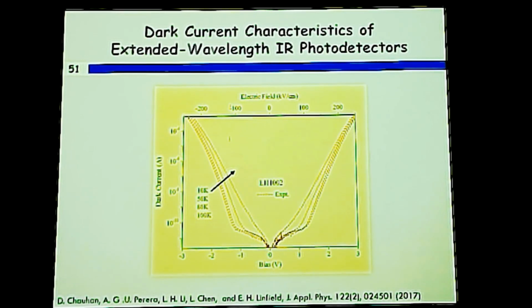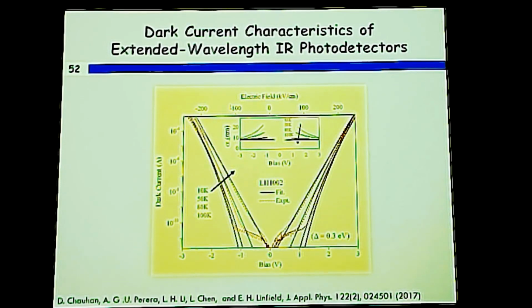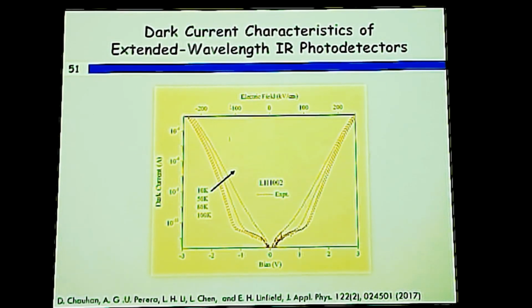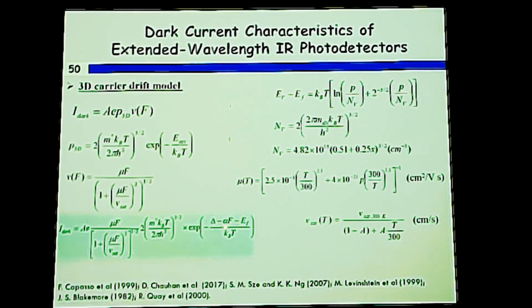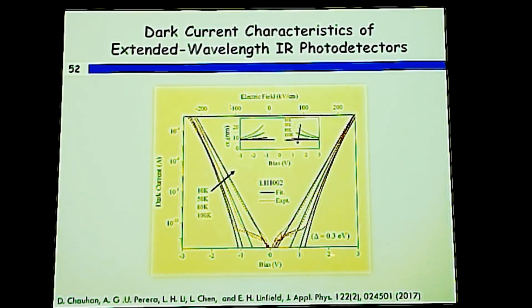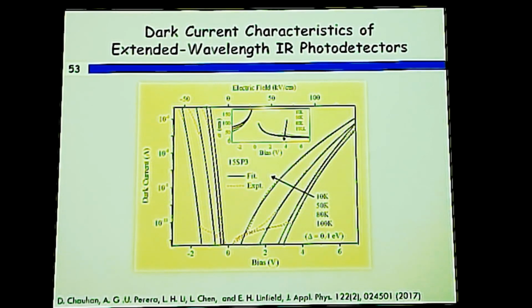So this is the experimentally measured dark current for the reference device without the extended wavelength mechanism. This is the fitting, and these are the fitting parameters, alpha. So we use a delta value close to the design for this device, which was 0.3 electron volt, and we obtain the fitting. In similar fashion, for the extended wavelength detector, we also use the delta value from the design, and we found this fitting.